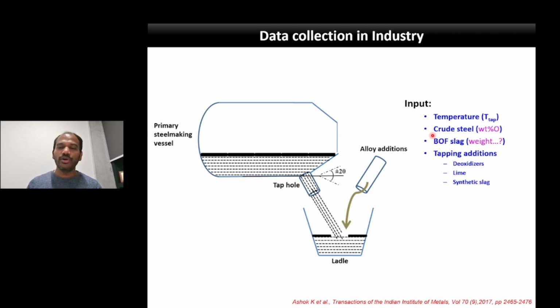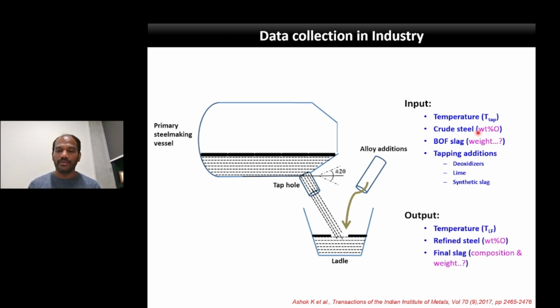For the crude steel composition also, it is not always possible to get the weight percent oxygen. So we have computed it in such a way, the program is given in such a way, in the equilibrium calculations. Initially, we will also calculate the weight percent oxygen, and then we will go for estimation of slag carryover. So finally, the output of the process is the LF temperature. You can see, once the tapping temperature and after the process, and once the ladle reaches the ladle furnace, what is the temperature?